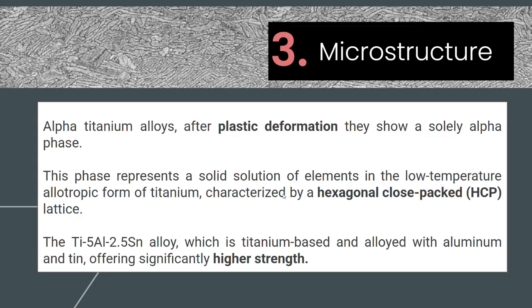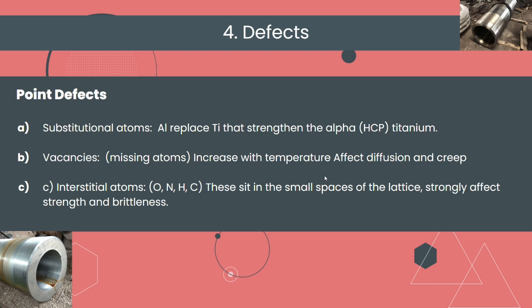Now, if we go pretty small and look at the microstructure, we can see that after the plastic deformation, it is a solely alpha phase, meaning that it is a solely titanium phase, and the shape or the phase represents a hexagonal close-packed structure, HCP, like I mentioned before. Most of it is titanium based, but the aluminum and the tin each offer some strength, just make it stronger.